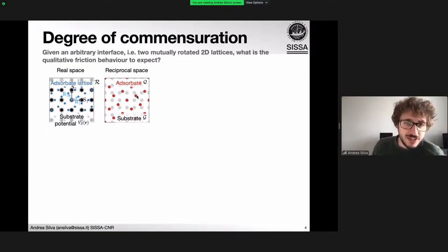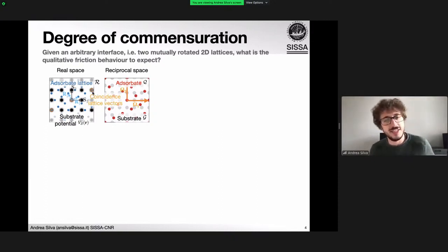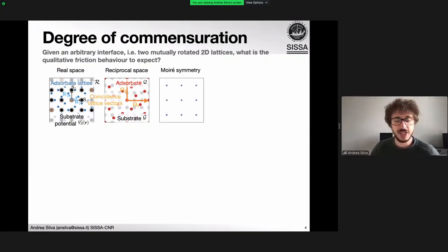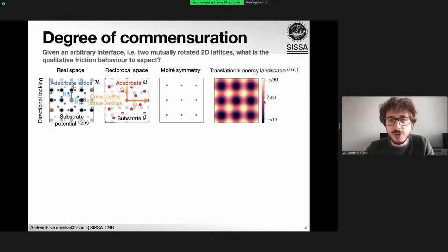The frictional quality of the contact at this nanoscale contact, at least in this theoretical extended world for now, is given by the appearance of a coincidence lattice vector, which is when the two lattices match, so that they can interlock nicely and give rise to high friction or structural lubricity. So these coincident lattice vectors are related to the moiré I was saying before, that gives the quality of the contact, and we can reduce these lattices to understand the moiré symmetry of the contact. And by translating the adsorbate lattice over the substrate, we can compute the translational energy landscape of such a crystal interface. So in this case, we will have directional locking, so the system will move along the preferential direction of the substrate.